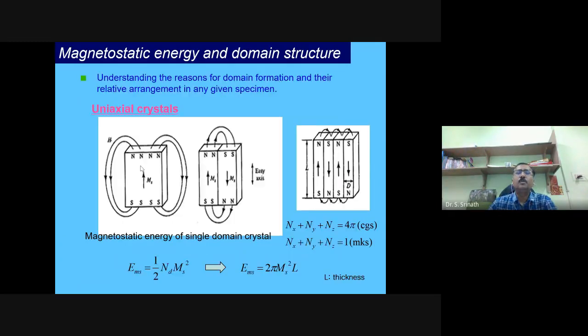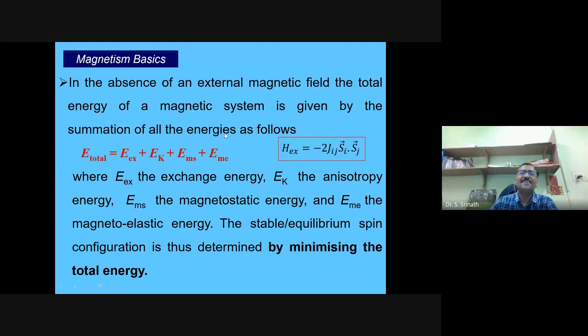Okay. So I wrote another term here, the fourth term, which is the magnetoelastic energy. That actually is coming into the picture and deciding the size. Why? Because whenever you apply a magnetic field, because of the spin orbit interaction, the dimensions of the material also will get affected. They can be positive mostly, and sometimes it can be negative also.